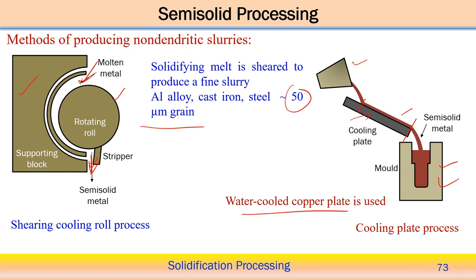In all these cases, it creates non-dendritic slurry, not dendritic slurry, because there is no option to create any dendritic structure. A dendritic structure will form if you do not disturb the liquid metal or apply some kind of external aid. If the stationary liquid metal is allowed to solidify, it will try to produce a dendritic structure, but in this case the liquid metal is always moving and some convection current is always present along with it. That is why in all these cases we always produce non-dendritic slurry during the semi-solid processing techniques.